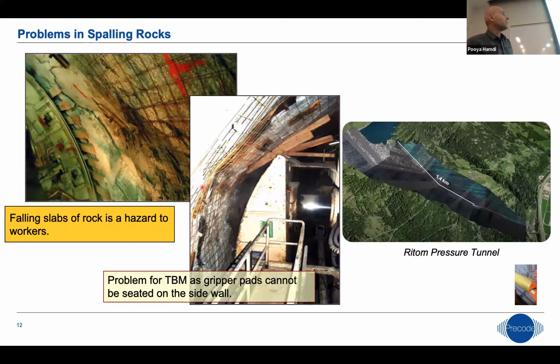The problem we can run into, obviously, when excavating the tunnel with a TBM, is that the gripper cannot push against the wall to go ahead. You end up having really soft, unsupported material that cannot sustain the amount of torque that is required for the TBM to go forward. A really nice example is a pressure tunnel in Switzerland that we visited last year. To give you a sense of how critical spalling becomes for a TBM, there was a 700 meters of elevation gain, and the tunnel was going horizontally up to this stage and then going upward between 45 and 60 degrees. So the whole procedure from here to the top was using a TBM.